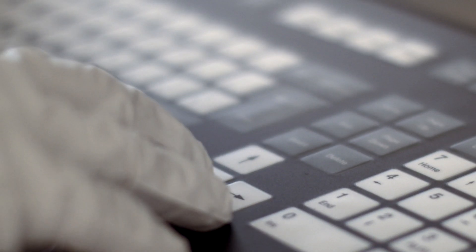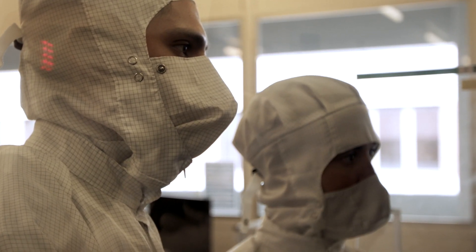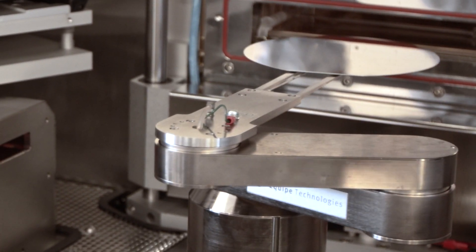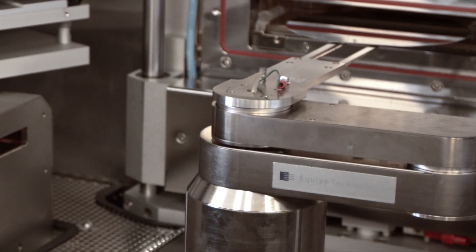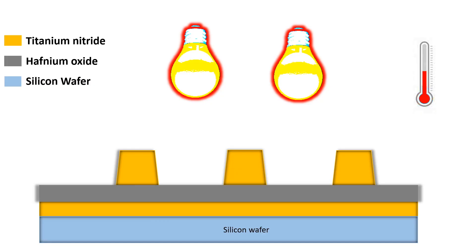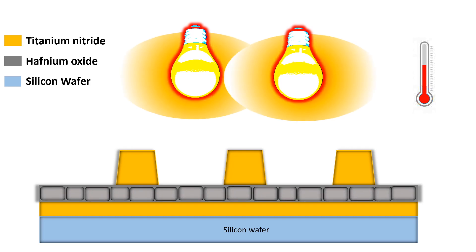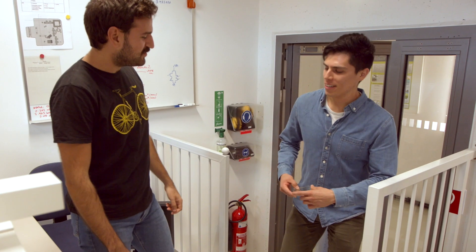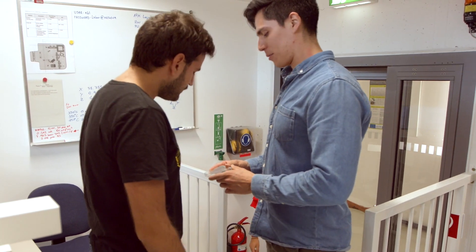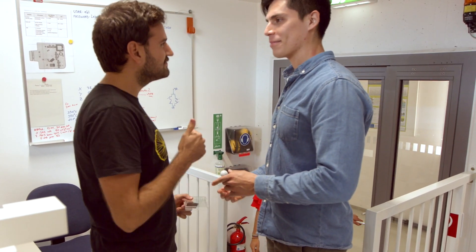We need to heat the whole wafer with the capacitor on top to convert the amorphous dielectric layer to a crystalline ferroelectric layer. Rapid thermal anneals employ hot lamps to quickly heat the wafer to temperatures in the range of 400 to 1,000 degrees Celsius. Small crystallites grow to larger ones during the anneal. Now the ferroelectric capacitors are ready to be measured.